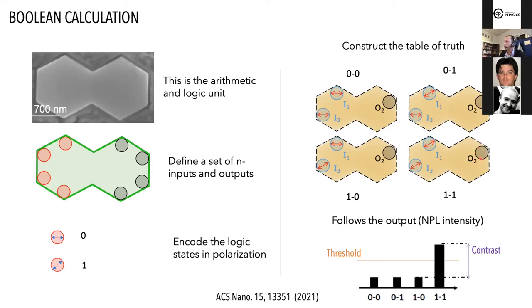And as in this example, that would be measured at O2. So here we're looking at the intensity of a signal as the output logic state. So if the output of the logic state is higher than a given threshold, here this is basically an example of an AND, okay? So you need to have one and one, with one encoded as this polarization state, and if we have a strong response at that corner above a threshold, then it's higher than all the rest, and then we have an AND gate.